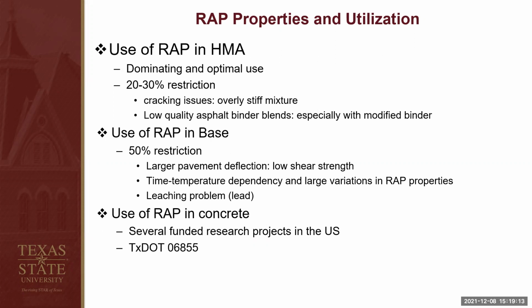And also we know asphalt is a viscoelastic material, and it will experience time temperature dependency. So we will tend to have lots of variations in RAP properties, and also the resulting pavement performance. And also back in old days, we still use lead in our gasoline, so that our RAP aggregates may contain lead, and this can cause leaching problems if we put RAP directly in the base.